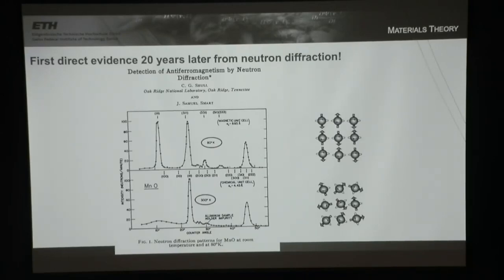And above the ordering temperature, you see the peaks in the neutron diffraction that correspond to the Bragg peaks that correspond to the crystallographic structure. The only order in the material above the magnetic ordering temperature is the ordering from the crystal structure, and these peaks are consistent with the known crystal structure of manganese oxide. But then below the magnetic ordering temperature, the symmetry is lowered because the manganese atoms become inequivalent. And we have additional peaks now.